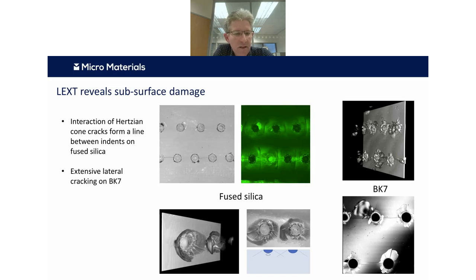And you can see there essentially that what appears to be happening is that it's this interaction of these Hertzian cone cracks that forms these apparent lines that you see subsurface. In contrast, there's an extensive lateral cracking on the BK7 glass.